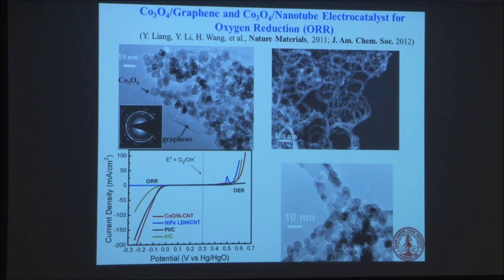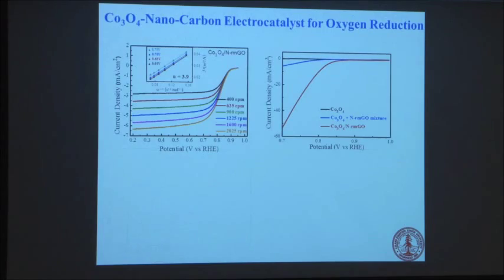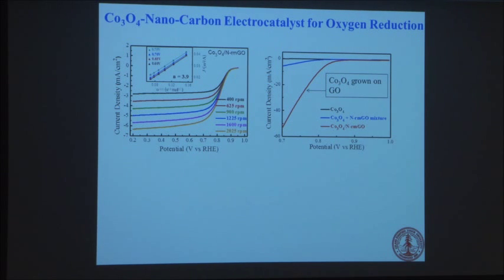So it's actually bifunctional as well. We can get ORR and OER with the same catalyst, okay? And the performance is pretty good. What I want to mention is really when we grow them on the sheets, okay, so this is current of oxygen reduction, it's really much better than when you grow them and mix with carbon. Okay, this is true for a lot of materials, okay. So we really think that strong coupling there is helping.